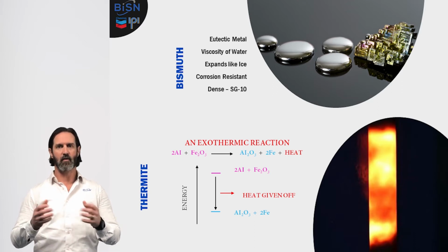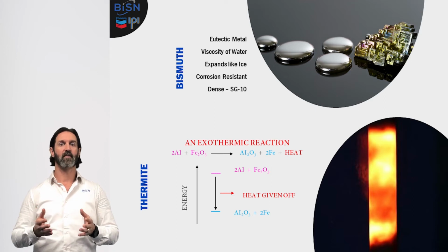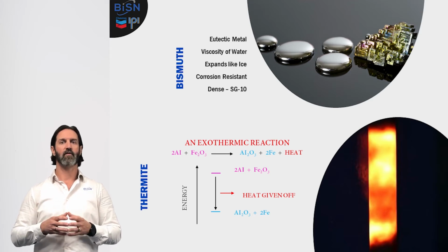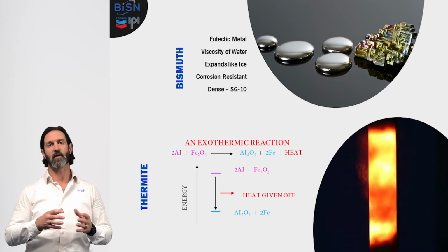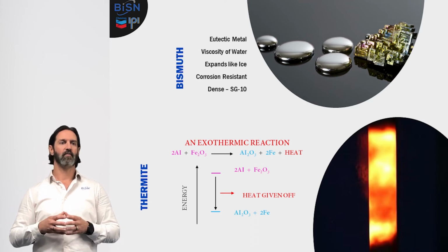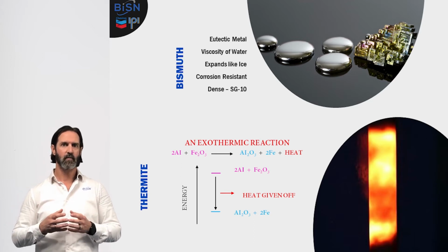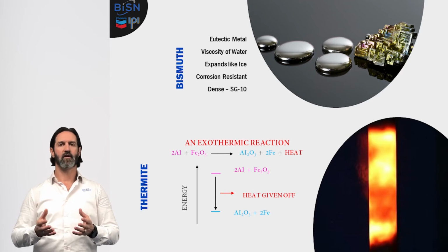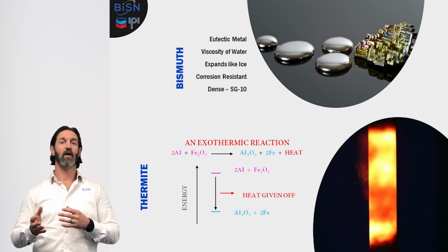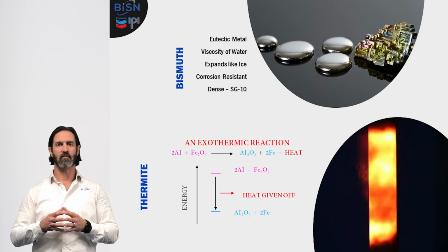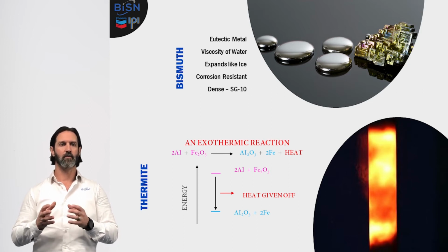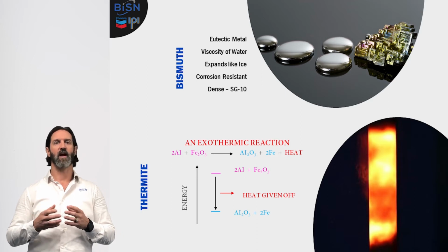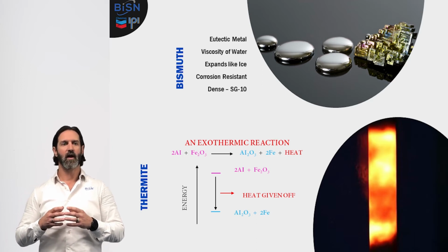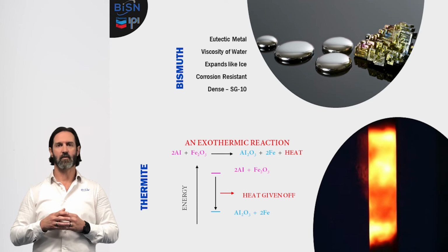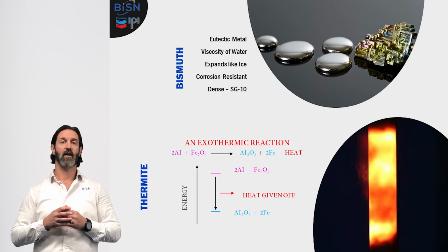So I said bismuth alloys because we do use bismuth as the main component of these different plugs, the alternative to cement. And some of the unique properties of bismuth is it's a eutectic material, meaning it solidifies and melts at basically the same temperature, a very sharp melting solidification point, meaning it's either solid or liquid. It doesn't go through the gel phase. Also has a viscosity very similar to water and has a very high density with a specific gravity of 10, so 10 times heavier than water.